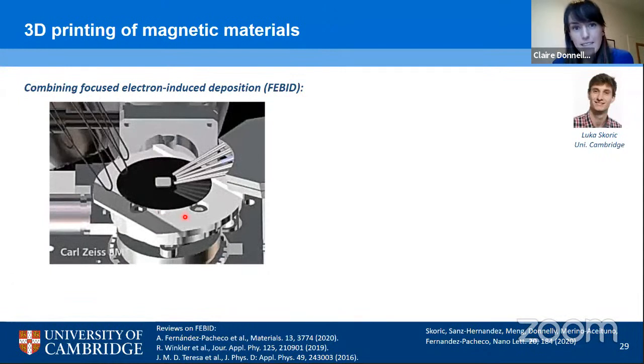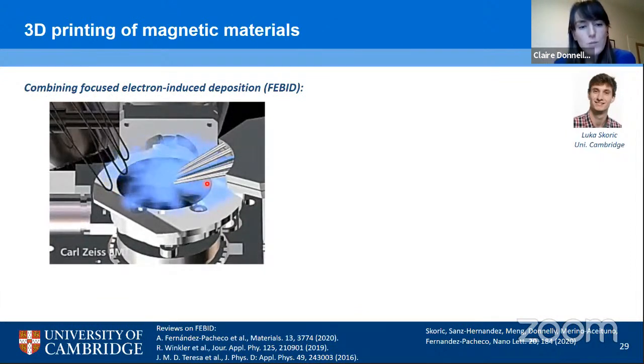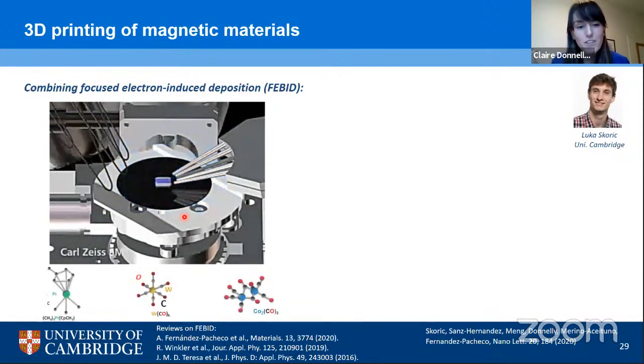So before we go into details of Luka's work, we can first of all take a second to remind ourselves what FEBID is. Essentially, we have a scanning electron microscope that has the ability to implement scanning beam patterns. And we inject a precursor into the chamber, and we can locally deposit the material using a focused electron beam. Now, because we're using a focused electron beam, we can achieve depositions with very high spatial resolution in the order of tens of nanometers. And there's a number of different materials that can be deposited. Now, perhaps the most well-known ones are platinum and tungsten, which are relatively dirty. But what is very exciting for the magnetic community is that we can also deposit cobalt, actually with purities upwards of 95%.